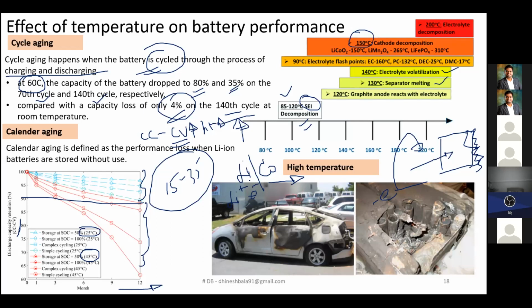And after you reach the temperature limit of 200 degrees Celsius, the electrolyte would get decomposed. So once the electrolyte is getting decomposed, you are just breaking the barrier wall between the anode and cathode. What actually happens is short circuiting might happen. So even that might be in one particular cell. So it might even create a catastrophic failure for your entire battery module, and the overall vehicle might face a huge disaster. So this battery performance is highly related with the temperature condition, and this temperature should be effectively monitored at any point of time.